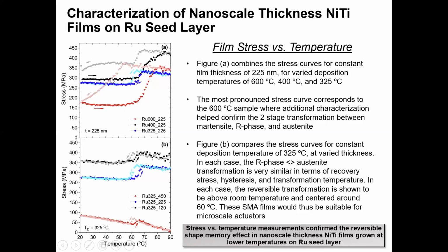And then I'll also say, while we stop on this slide, the one done at 400 degrees, which is this black and gray curve, is characteristic of a two-phase transformation. So on heating, you've got the transformation between martensite and austenite. And then on cooling, this knee in the curve is most likely the R phase transformation, which is characteristic of a narrower hysteresis. And then from this point on, you're going from this intermediate R phase down to a partial martensitic transformation.